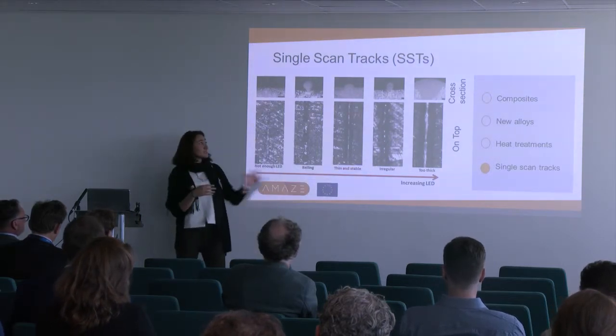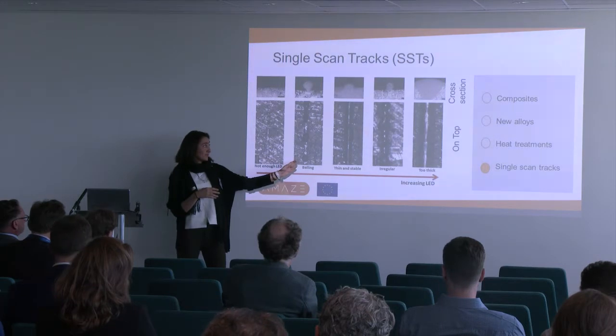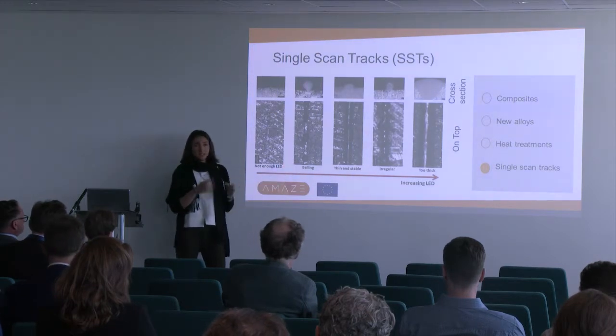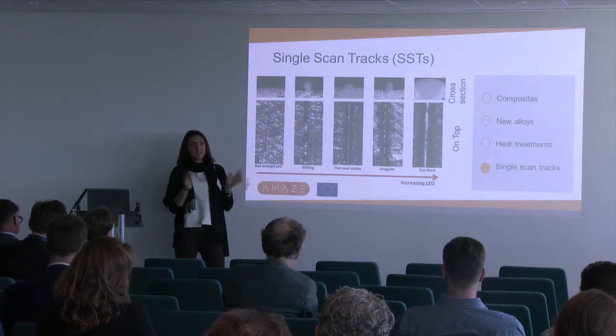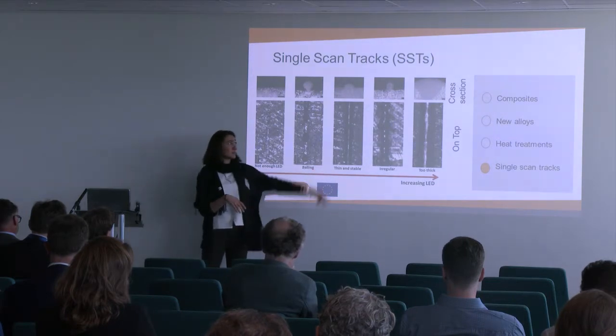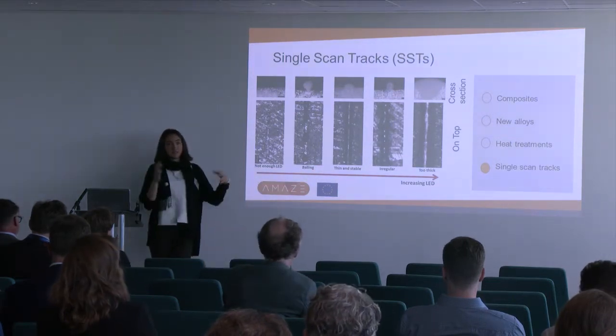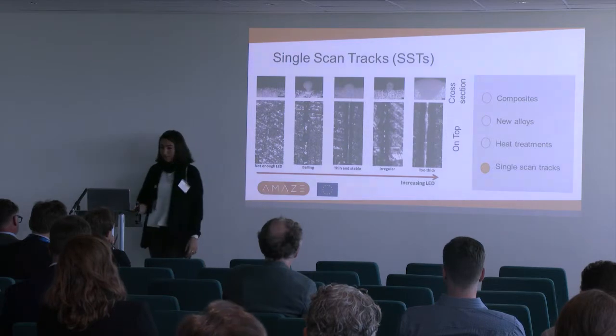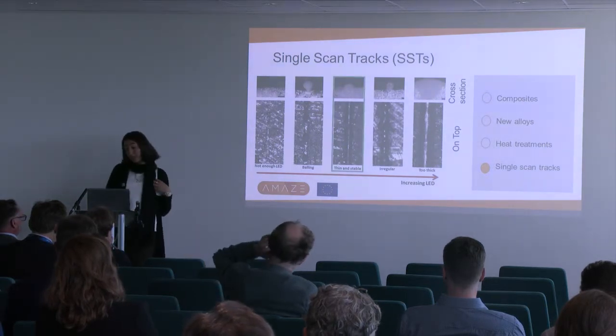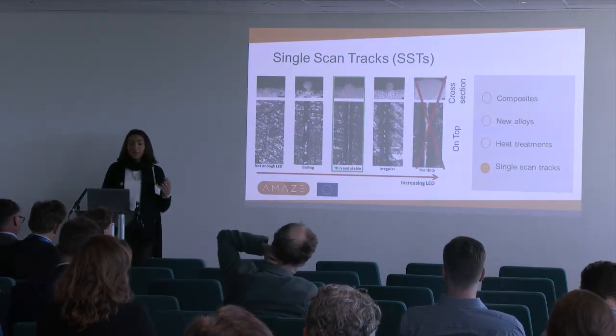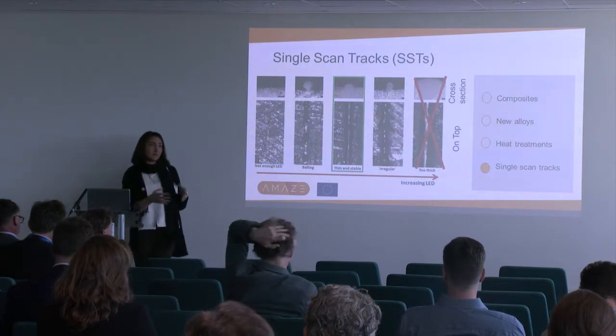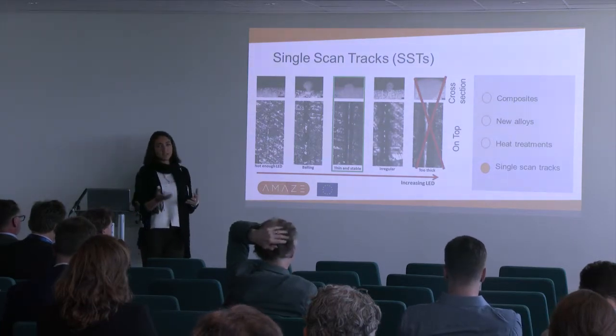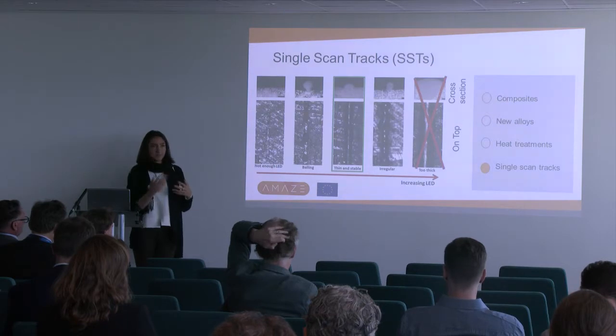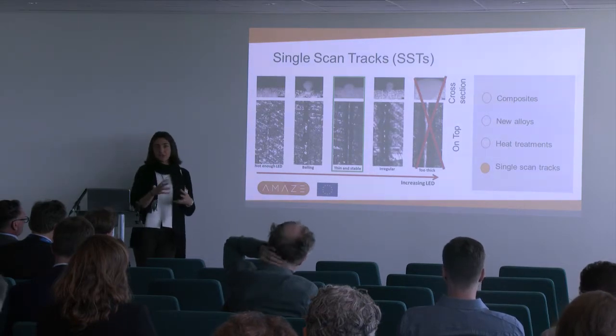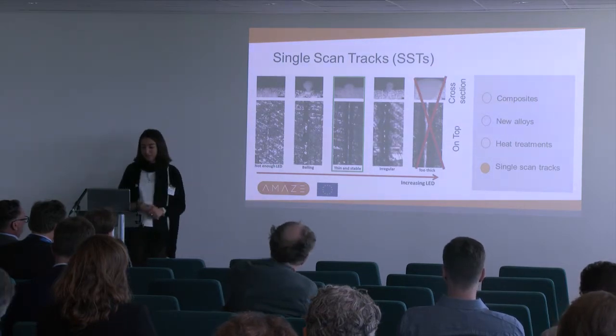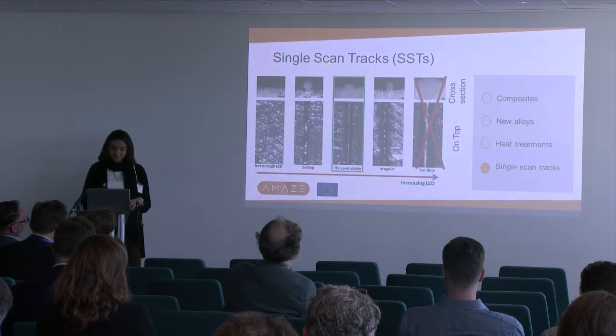In this case, this is a different irregularity with respect to the previous one. We can see that the scan is not broken, but it is strongly asymmetrical. And then we go to too thick scans, which are very large and very deep as well. So the thin and stable scan is the most promising one, while this one, even if it is stable, is not promising. It will waste a lot of power, it will probably dirty the machine, change the composition, and have a lot of negative effects.